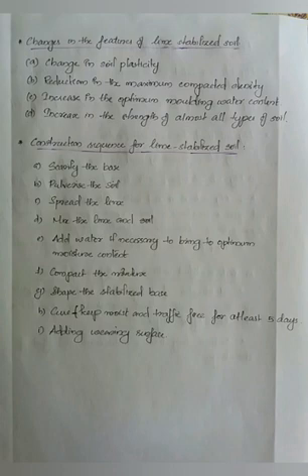Then the mixture is compacted and then shaped. After shaping, it is allowed for curing. An important thing to consider during this process is that it should be kept moisturized always and also traffic free for at least five days. And the last step is the addition of wearing surface. So this is all about lime stabilization.